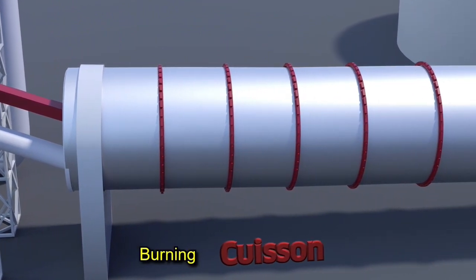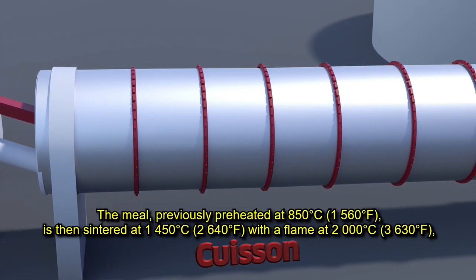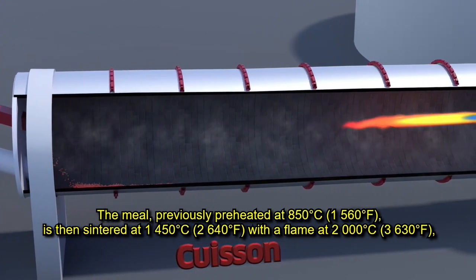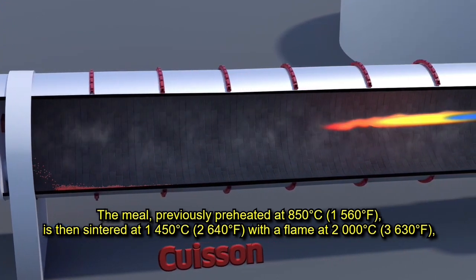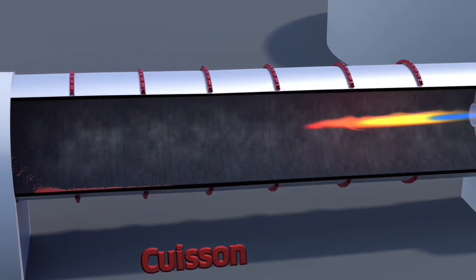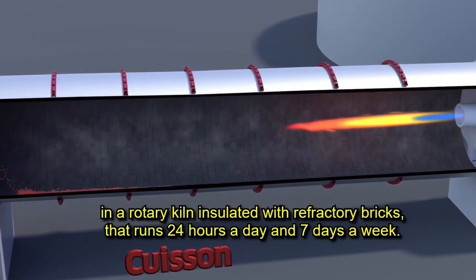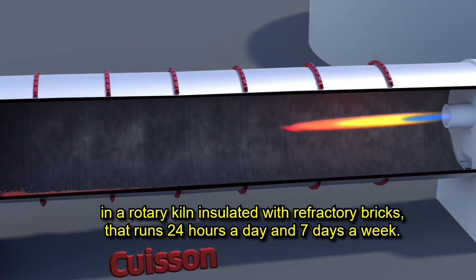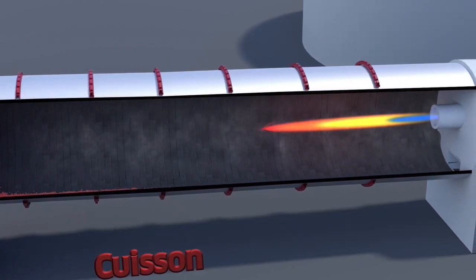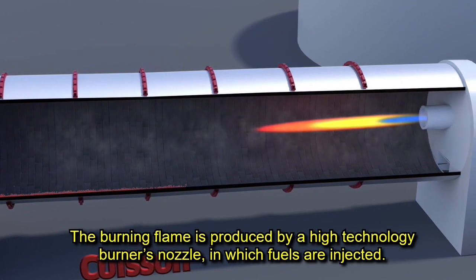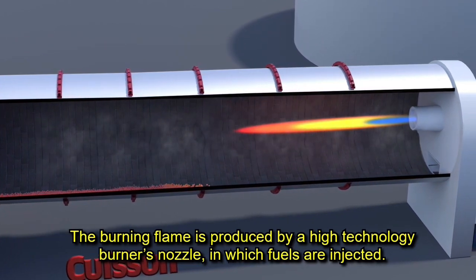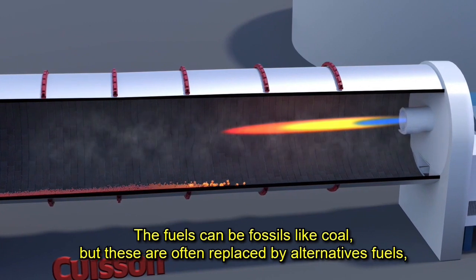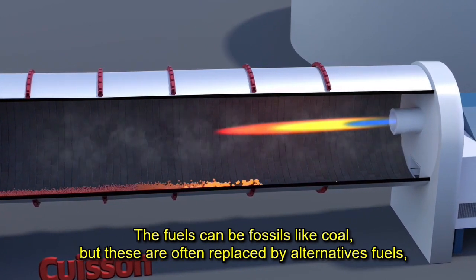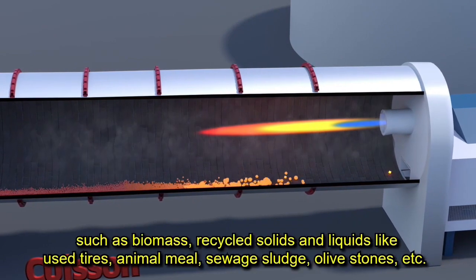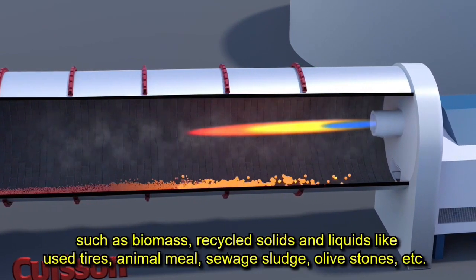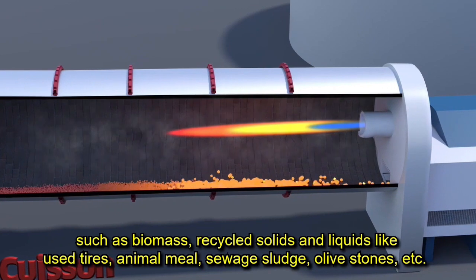Burning. The meal, previously preheated at 850 centigrade, is then sintered at 1450 centigrade with a flame at 2000 centigrade in a rotary kiln insulated with refractory bricks that runs 24 hours a day and 7 days a week. The burning flame is produced by a high-technology burner nozzle in which fuels are injected. The fuels can be fossils like coal, but these are often replaced by alternative fuels such as biomass, recycled solid and liquid like used tires, animal meal, sewage sludge, olive stones.